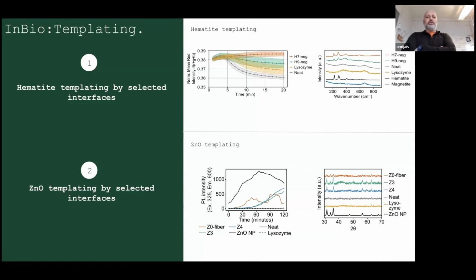the default output will be magnetite. And then we had a plate where underneath each, we had a magnet. So very quickly, we saw whether we form magnetite or something else. And you can measure it with a few different methods, but one thing you can measure is the level of red versus other things. And you can see that when we had nothing like a buffer or we had a lysozyme, very quickly you lose the redness. And I can tell you that also you see like ground black things around the magnet.